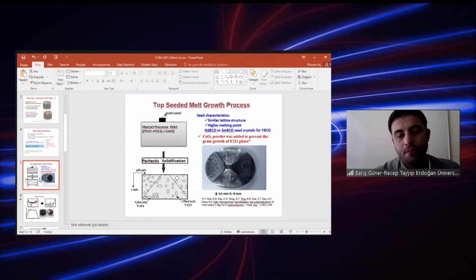The peritectic temperature of the seed must be higher than that of YBCO. So sometimes we choose neodymium barium copper oxide or samarium barium copper oxide seed crystals for YBCO. The seed must have a similar lattice structure, which is very important, and it must also have a higher melting point.